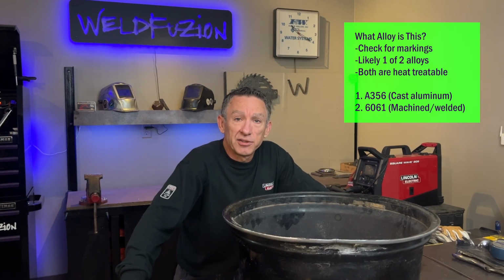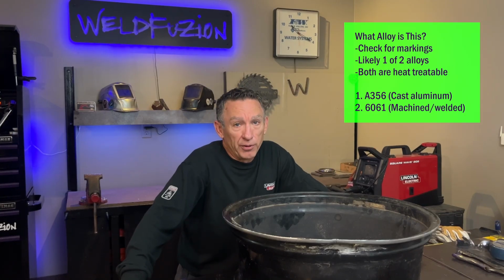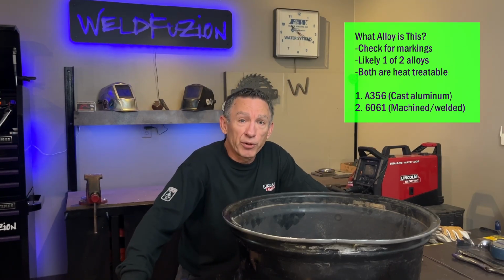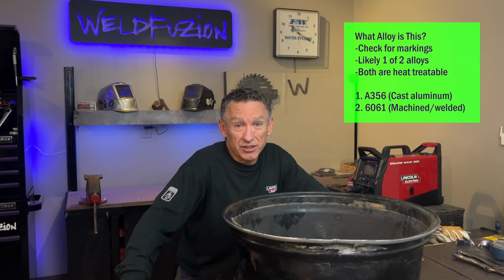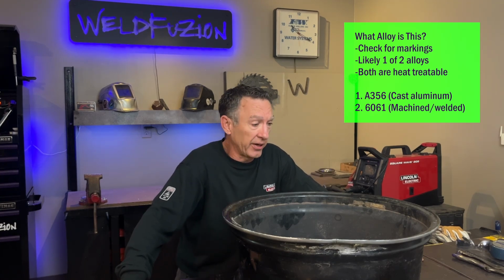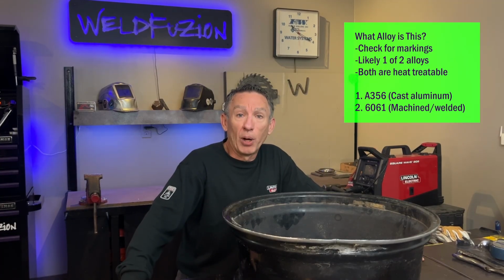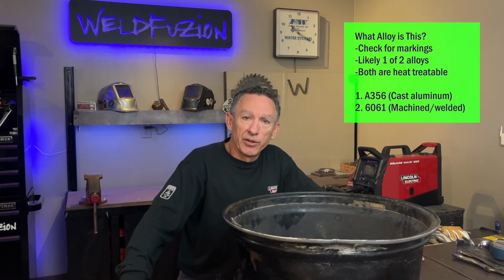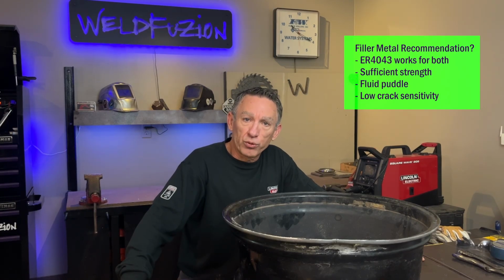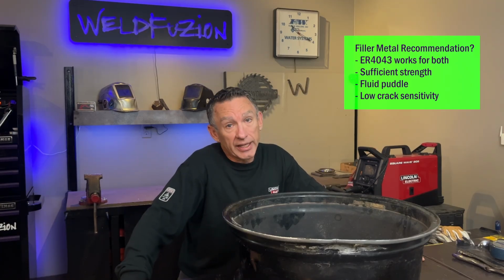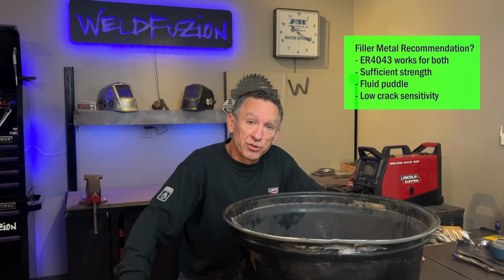So what alloy is this anyway? Unless it's stamped on the inside somewhere, we're just guessing. But thankfully, I found out that rims are typically made from two different alloys. One is the alloy A356, which is a cast alloy, readily weldable. The other potential alloy that it could be is a 6000 series, like a 6061, just depending on whether this was cast or forged or machined out, right? I don't think we're in that category right now. But if it were, the cool thing is ER 4043 filler metal is commonly recommended for both the 356 series, being the cast series, and the 6000 series alloys.